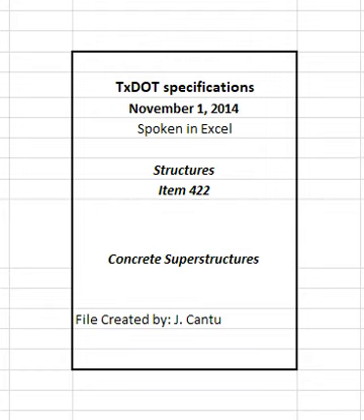Place concrete at a minimum rate of 30 feet of bridge slab per hour for transverse screeding unless otherwise shown on the plans. Deposit concrete parallel to the skew of the bridge so all girders are loaded uniformly along their length. Deposit slab concrete between the exterior beam and adjacent beam before placing concrete in the overhang portion of the slab. Furnish personnel and equipment capable of placing, finishing, and curing the slab at an acceptable rate to ensure compliance with the specifications. Place concrete in transverse strips.